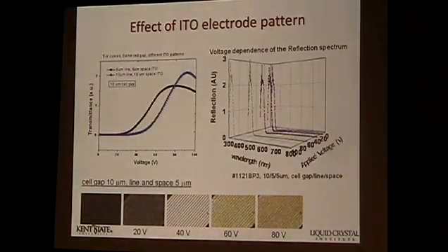Means the blue shift, right? What does blue shift mean? You have a cubic lattice, right? You have lots of cubes inside of the cells, and the cell size is more or less comparable to the wavelengths of light. And then you apply the field, they shrink, they get compressed, right? And they change the size of the structures, and so that's the reason that you see a slight shift.